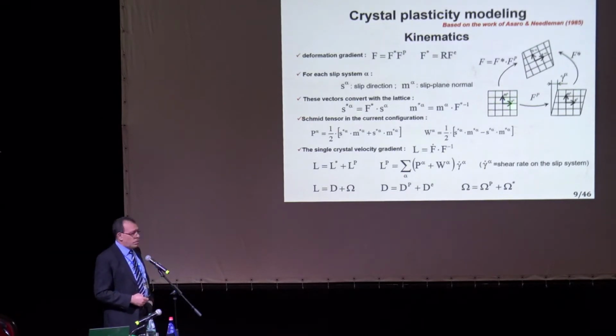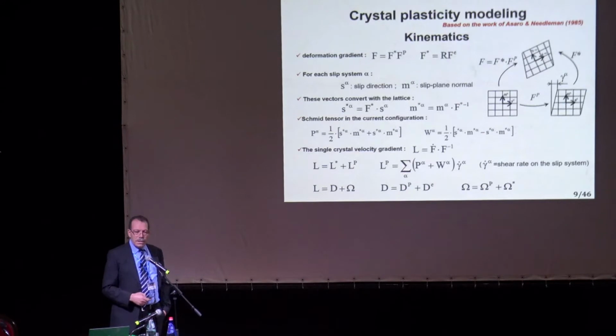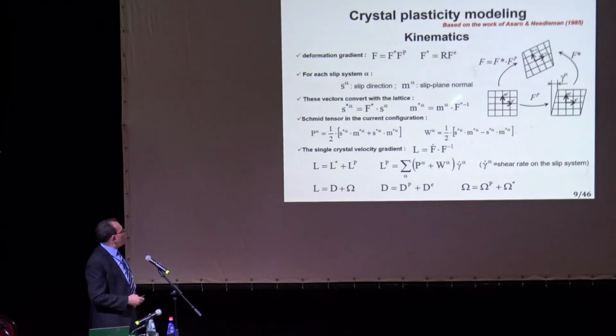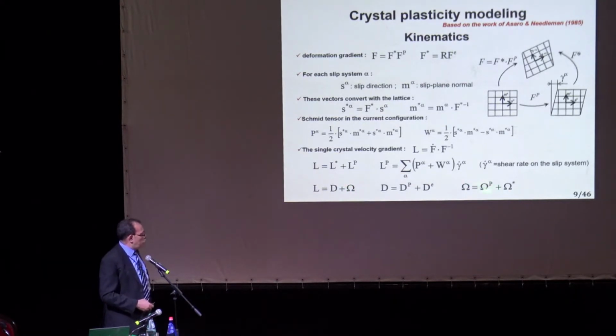So we have shearing on a given plane. That gives you the final configuration here of the crystal that has sheared. And in this final configuration, in fact, the shear plane normal and shear direction have rotated. And they have rotated through this F star here. So in fact, we don't have Fe. Elastic is F star, which includes the elasticity plus the rotation of the lattice. And then from that, we can, of course, this is the classical decomposition, get the velocity gradient and get the strain rate from the symmetric part of the velocity gradient and get the spin, which is the rotation rate. And then the spin can be decomposed into the plastic spin and what we call the lattice spin.